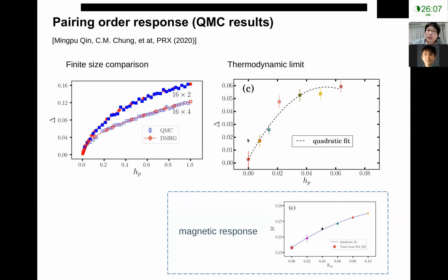Then we study what the pairing order is when we decrease the pairing field to 0. This is mainly done by Monte Carlo, because Monte Carlo can handle very big system sizes, so they can extrapolate to the thermodynamic limit to make this analysis possible. We found that if we decrease the pairing field, the pairing order also decreases continuously to 0.